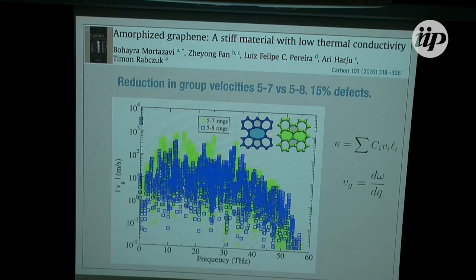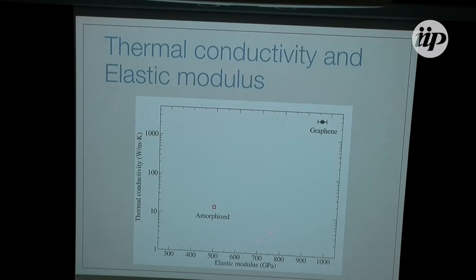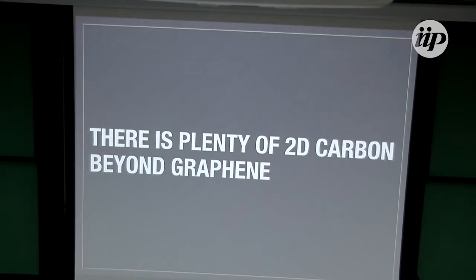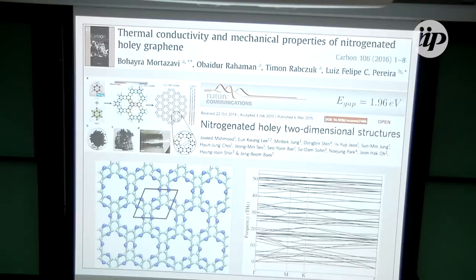We also looked into which kind of defect was worse for the thermoconductivity, or at least for the group velocities. And we see here that these 5-8 rings, or pentagon-octagon rings, have lower phonon group velocities in general than when you only have defects like pentagons and heptagons. If I do a graph of thermoconductivity as a function of elastic modulus, this is in a log scale, my thermoconductivity in watts per meter Kelvin, elastic modulus in gigapascal. Graphene is all the way up here, and this amorphized graphene is down here. Now, there's plenty of 2D carbon beyond graphene, and what I'm going to try to do is to keep adding points to that graph.